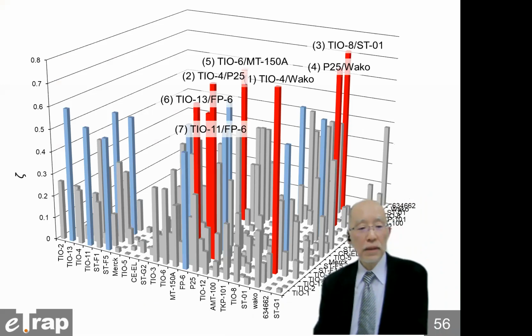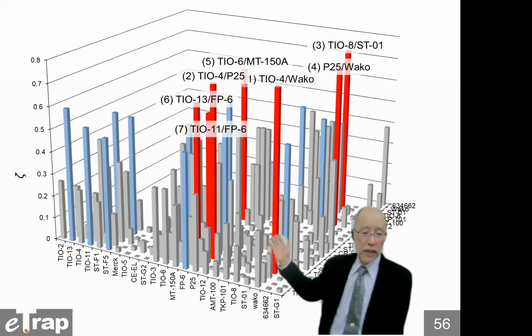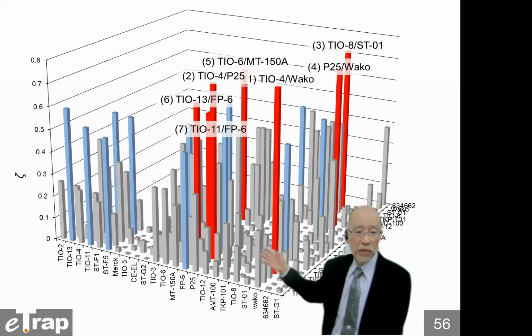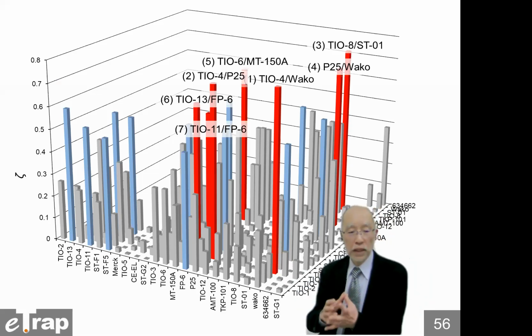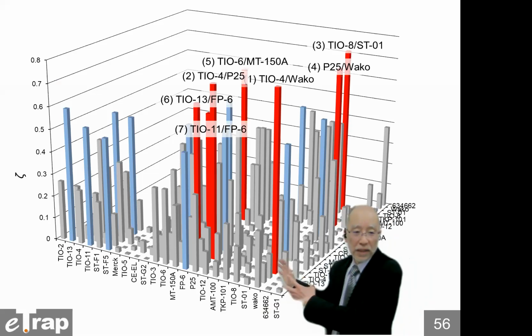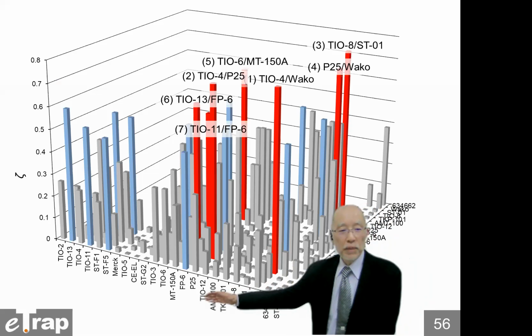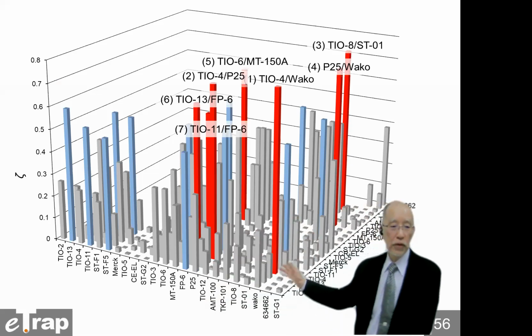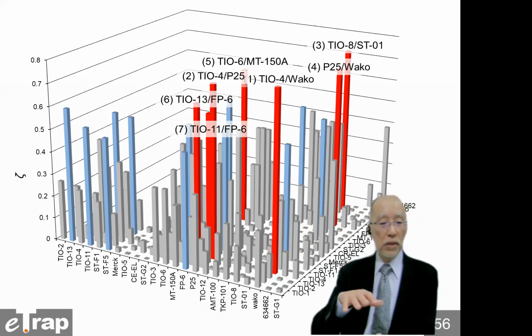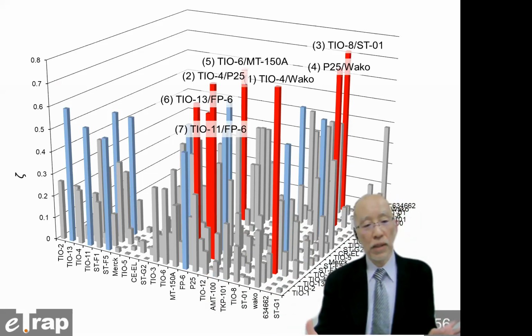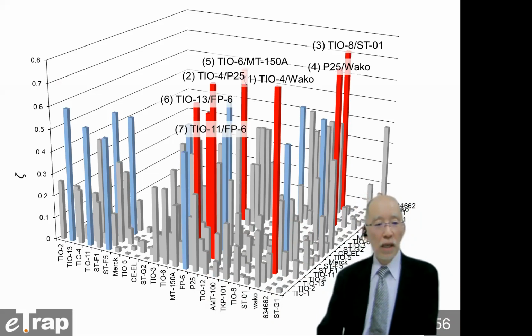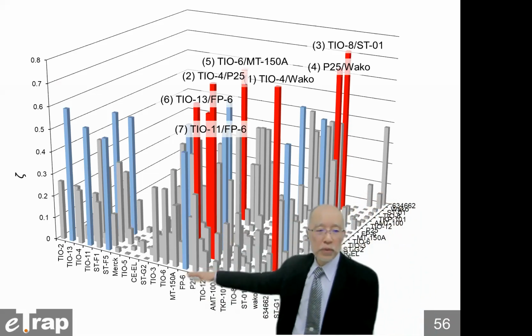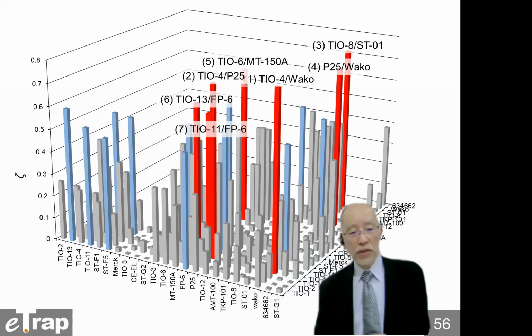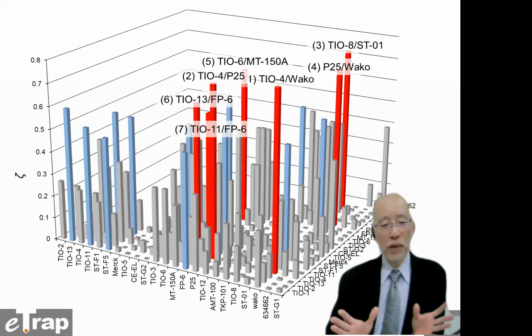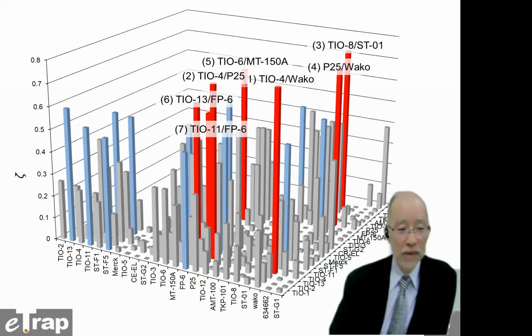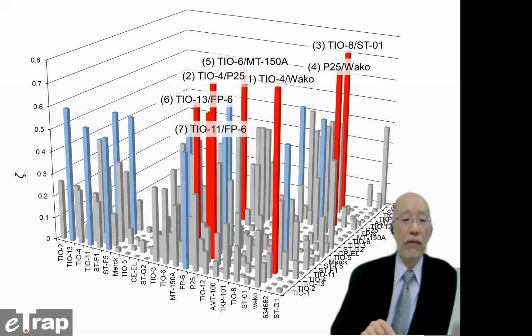Okay, then, this is part of the results of degree of coincidence measurement for pairs of commercial titanium oxide samples. This is only a part, and you can see the degree of coincidence is very low for almost all the pairs of commercial titanium oxide samples, lower than 0.5 or even almost 0. That is natural, because they are provided as different titanium oxide samples. So it is natural to see such a difference.